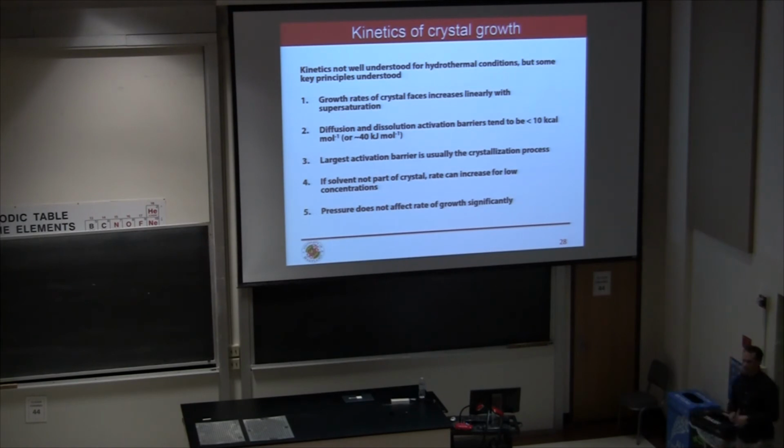So again, I've mentioned this slightly before, people think of it as a black box reaction. The kinetics of the crystal growth is not very well understood, but it's still actively studied. We actually have a collaboration with 17BM at Argonne National Lab where we do in situ hydrothermal powder diffraction, where we set up a hydrothermal reaction in a quartz tube and then do 3-day runs where we'll take an X-ray image every 5 minutes and just see how the different intermediates are being formed and how the crystal growth happens. But it's still an active field of investigation.